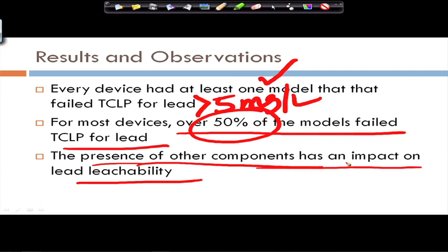that's what I was trying to tell at the e-waste conference we had last year in XLRI Jamshedpur. I don't know if some of you were there, but in that conference I was discussing some of the research work that I was involved with. I said that as we go to newer and newer electronics, which means less iron and more plastics, within the presence of less iron, lead leachability is more. Percentage-wise, lead leach is more when we have less iron present.